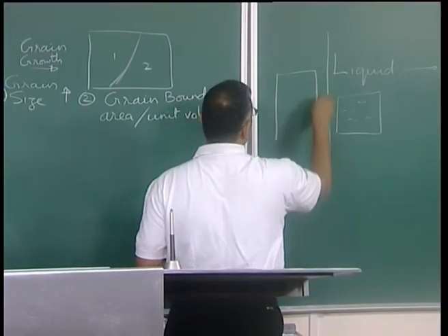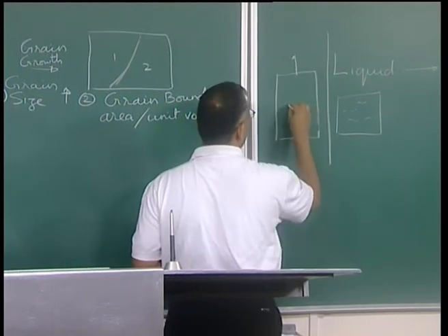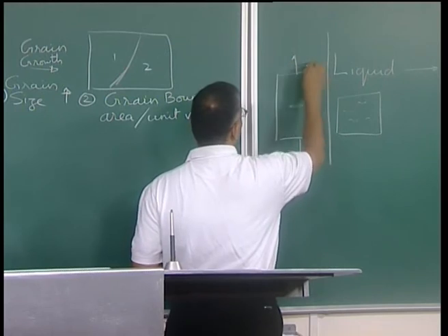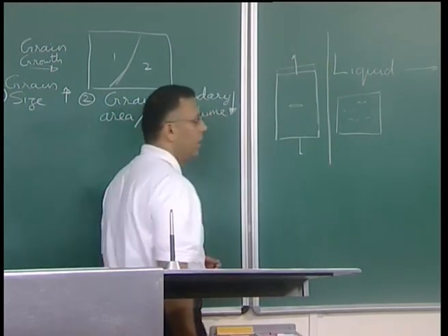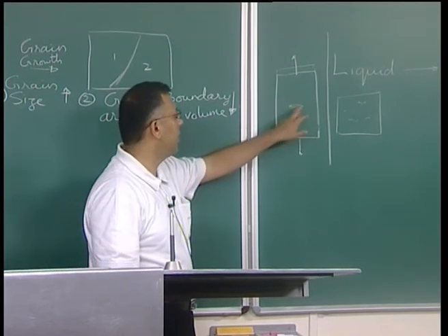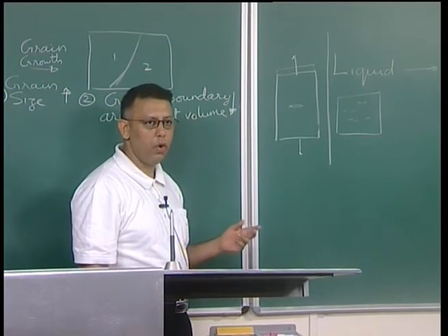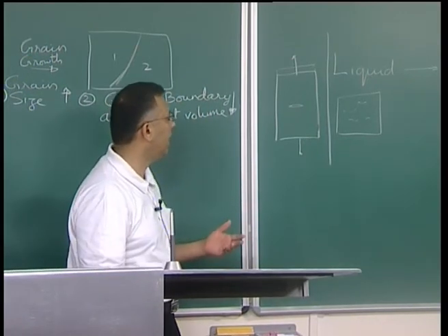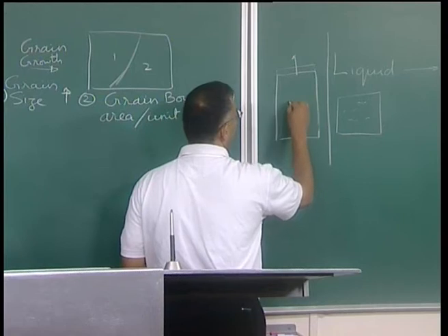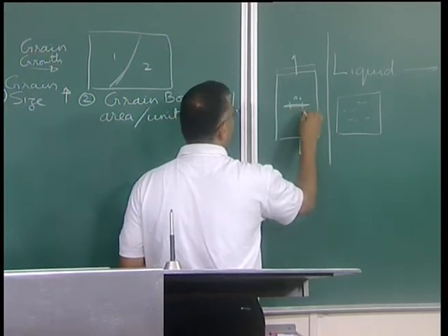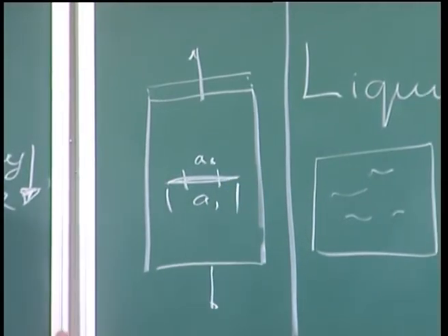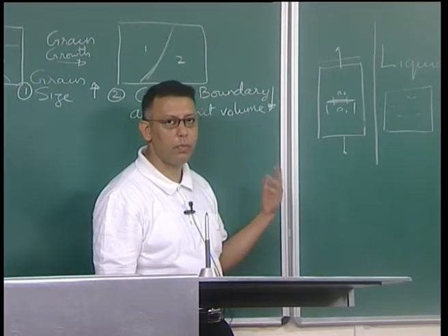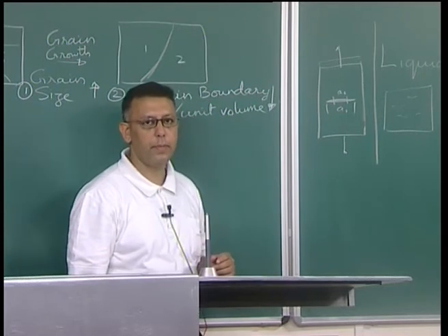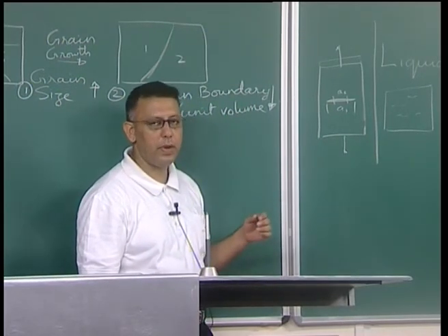To give an example, suppose I have a material with a crack in it. Suppose I have a large body in which I have a crack, and I cause the deformation of this body, stretch it a little bit and hold it. Then the strain energy stored in the material can drive the crack growth. Globally, suppose this crack grows from this length to a longer length. So, my original length is A0 and it grows to a longer length A1. Then the strain energy is relieved, and part of it goes to the formation of the interfacial energy or the broken bonds, and the overall strain energy of the material comes down.